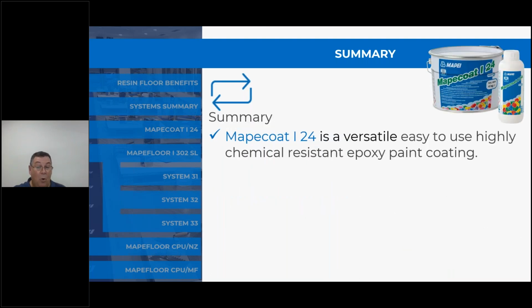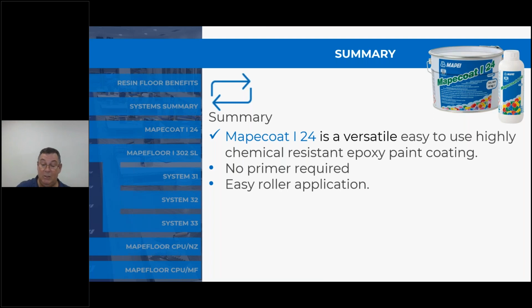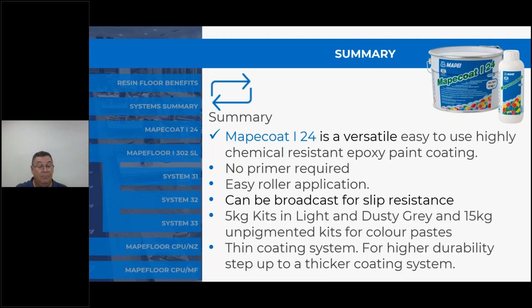In summary, the I-24 is a versatile, easy to use, highly chemical resistant epoxy paint coating. There's no primer required. It's easy roller application, so the skill set is not too high. It can be broadcast for slip resistance. It comes in a 5 kilo pigmented light grey or dusty grey, or in a 15 kilo unpigmented that pigment pastes are applied to. It's a thin coating system. For high durability you step up to a much thicker system like the I-302.